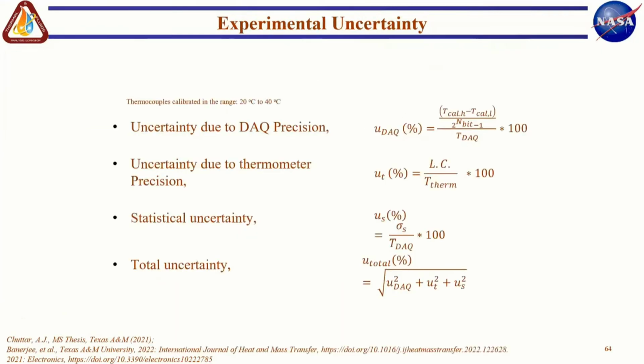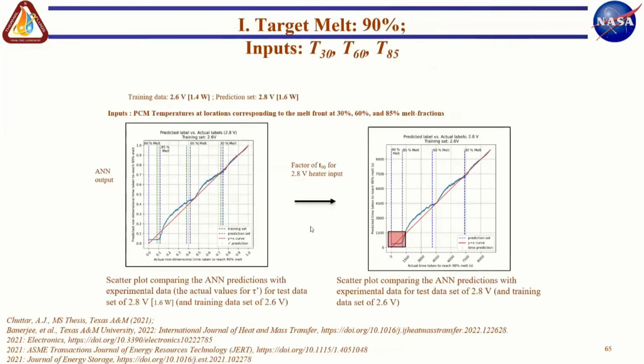And let's see. So these were the uncertainties in our measurement in the experimental data. And here is the prediction versus what we observed in the experiments. So what you see in the graph on the left is we took the 2.6 volt experimental data. We trained the ANN model with that data for the 30, 60, and 85% melt fraction thermocouples, and we predicted it for the 2.8 volt experiment. And so on the x-axis, we have plotted the non-dimensional value of the time taken to reach 90% melt.